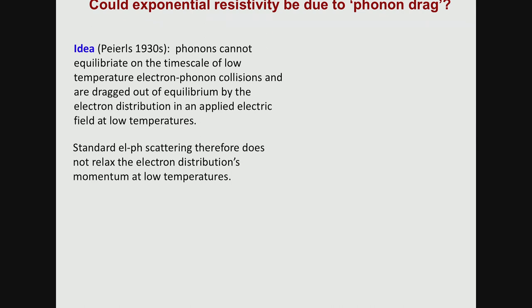And the reason that this is happening is a very interesting one. It actually goes back to an argument that Peierls had with Bloch in the 1930s. Bloch postulated the standard laws for the electron-phonon resistivity of metals, and that involves a really big assumption, because it's saying that you have your electrons scattering from your phonons just in equilibrium, the material sitting there. Then you apply a voltage, and you give the electron assembly some momentum. The assumption of the Bloch-Grüneisen law is that the electrons are scattering off the phonons while this is happening, but without giving any of that net momentum to the phonon assembly. So the phonons are staying at zero net momentum, decoupled enough from the electrons that they can equilibrate, but coupled enough that they can scatter the electrons.